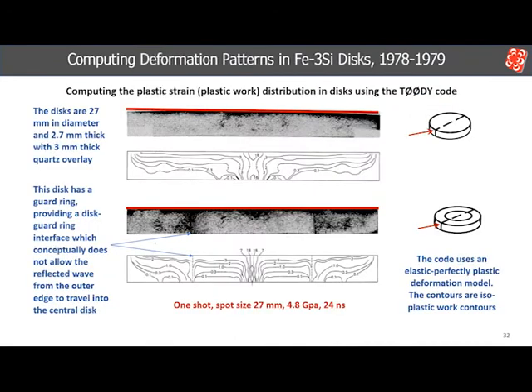At about this time, we attempted to determine whether the plastic strain distributions observed in the iron silicon discs could be computed. Computations were made using a 2D finite difference code based on an elastic, perfectly plastic material. The output is in isoplastic work contours, which would be proportional to the intensity of the plastic strain. Both discs shown here were given the same shock conditions with quartz overlays. The etched surface of the shock disc is shown above the computed contours of plastic strain.